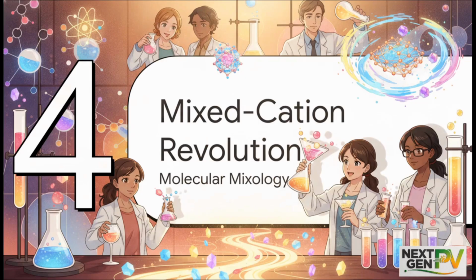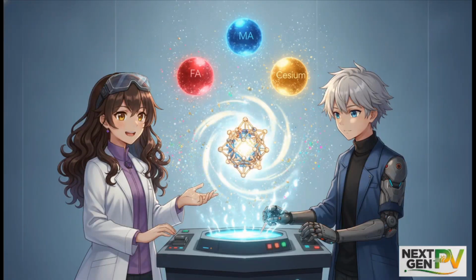Which brings us to a huge breakthrough in Section 4, the Mixed-Cation revolution, molecular mixology. To solve these massive degradation issues, scientists basically had to become molecular mixologists. The modern standard completely throws out the idea of using just one compound. Instead, the best cells today use engineered mixtures. They combine formamidinium, methylammonium, and purely inorganic cesium, creating a triple-cation perovskite, and then they mix in different halides.